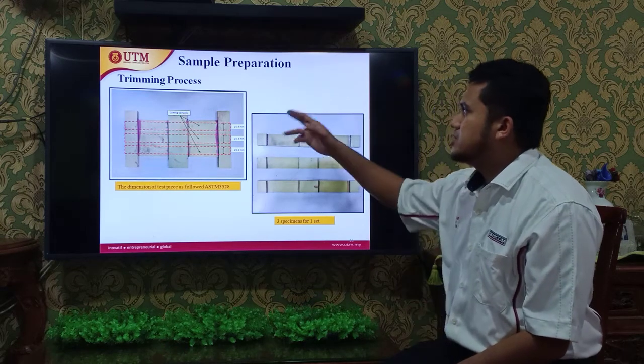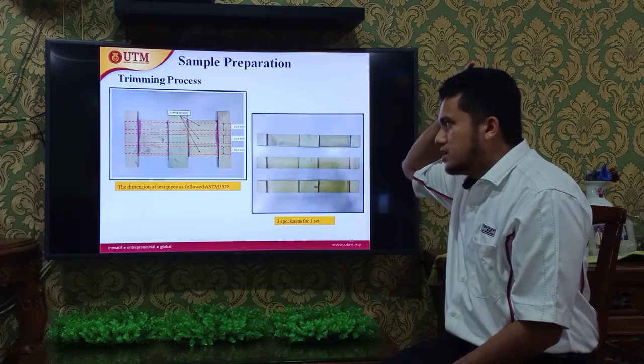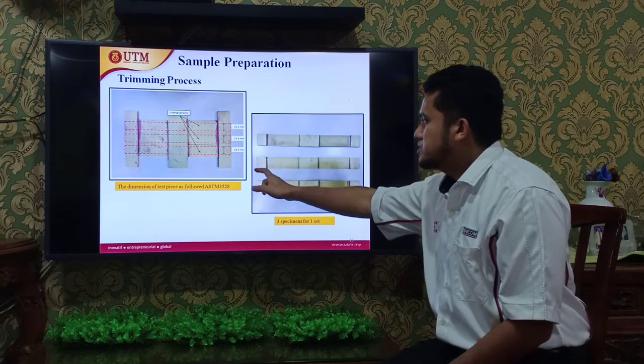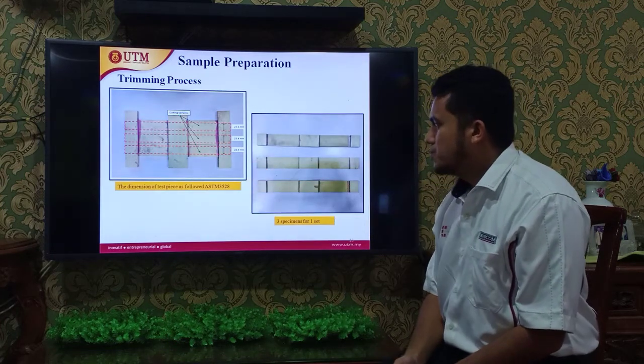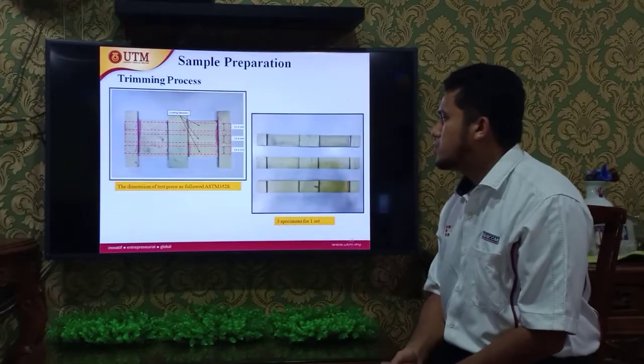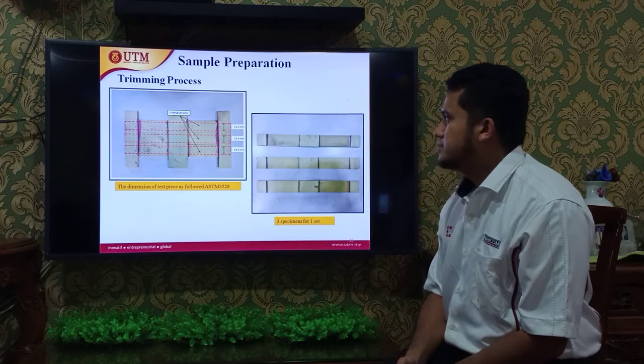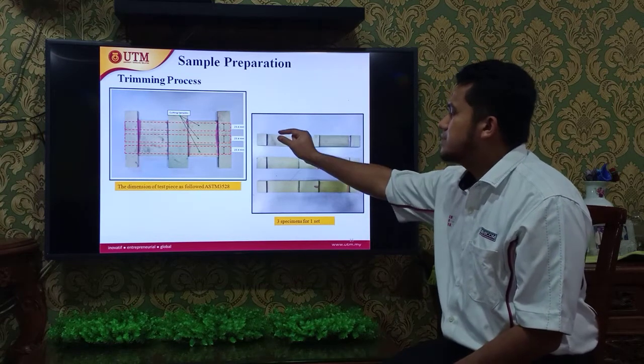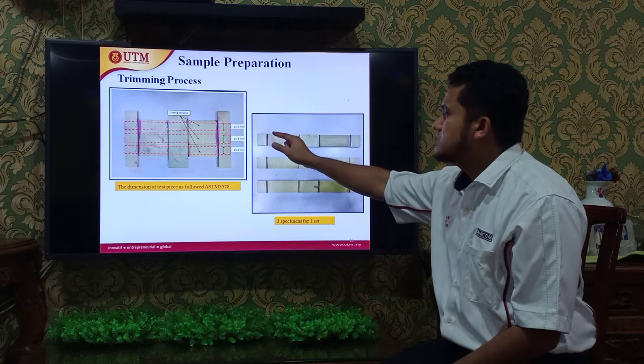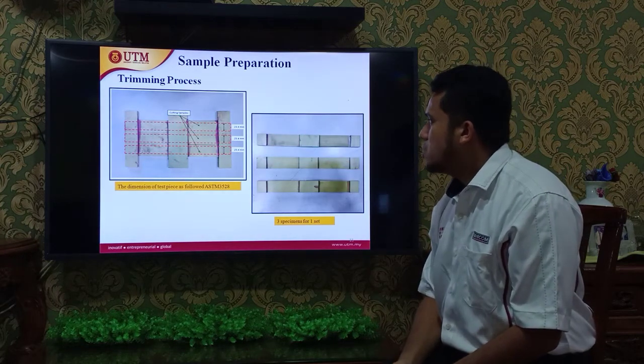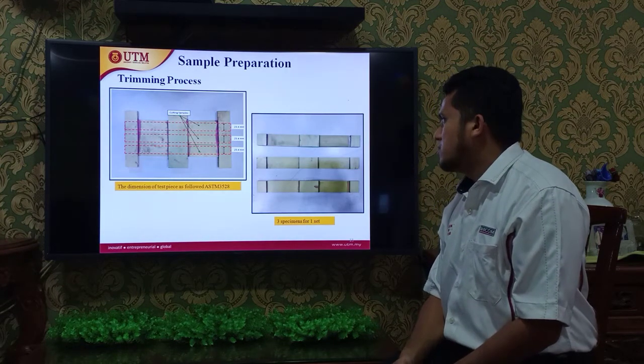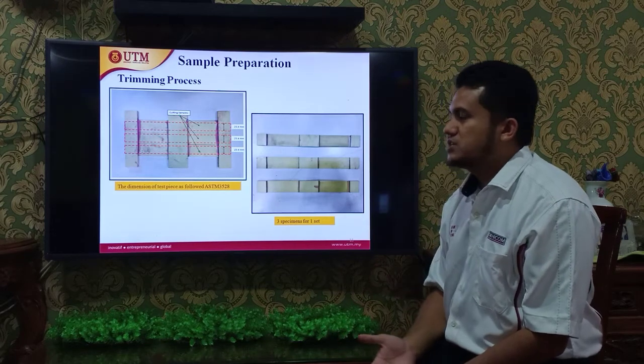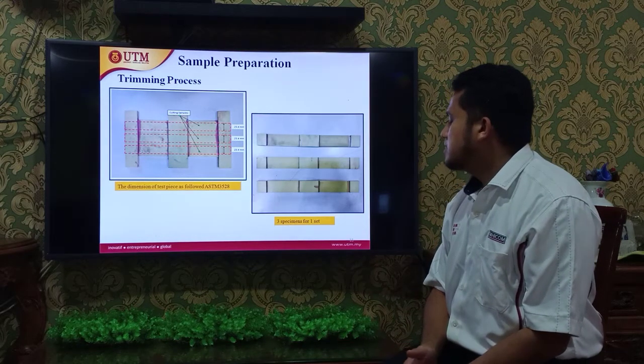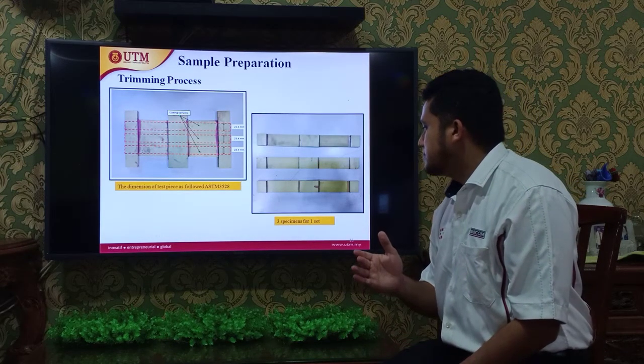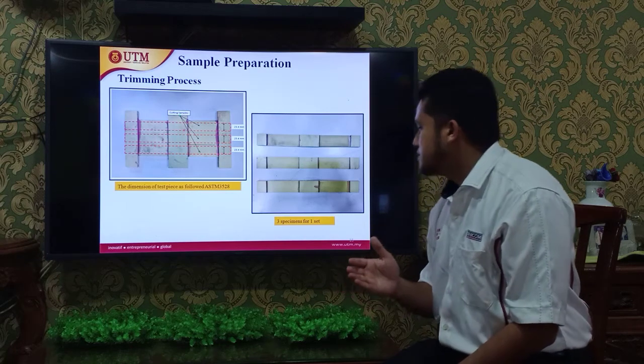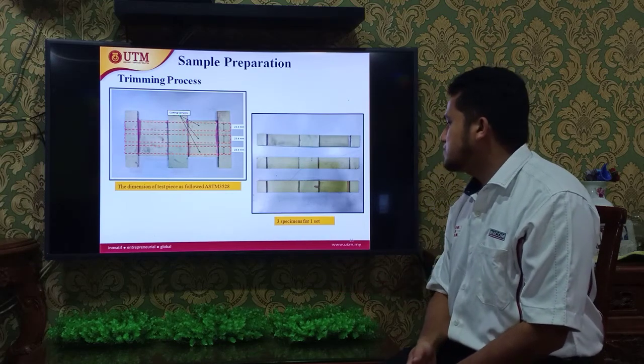Okay, this is the trimming process activity. In this picture, the dimension we want to test is as per ASTM 3528, where the width of the sample is 25.4 millimeter. For every test panel, we must make 3 specimens for 1 set.